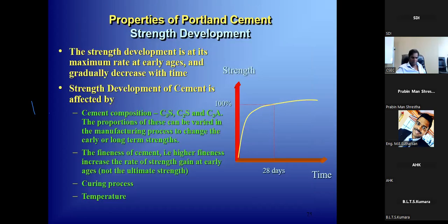I'll leave it there. But then just a very brief one, why we measure at 28 days, strength on the y-axis, time on the x-axis, 28 days. See, most of the strength is developed in the first 28 days. That's why we have the characteristic strength measured at 28 days. It's not a magic number, it just happened to be there. But with the newer concretes, we still use 28 days, but now, more and more, we are using 56 day strengths. And we can use 1 year strength. If you're designing a structure where occupants only come after 1 year, you can smartly use the elastic modulus, the strength increases by about 15%. I normally use about 15% increase.